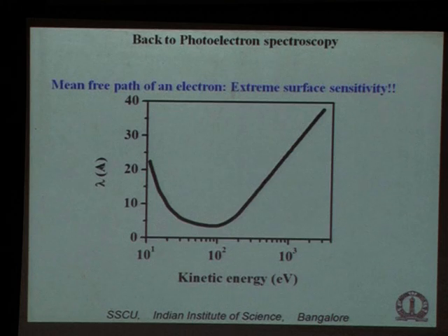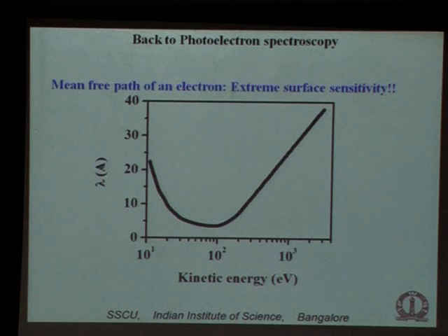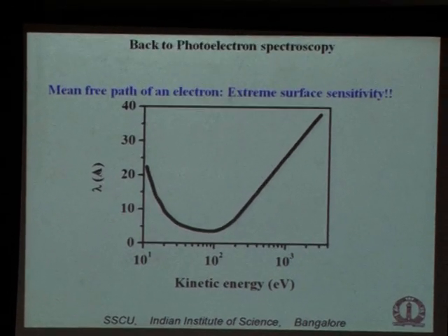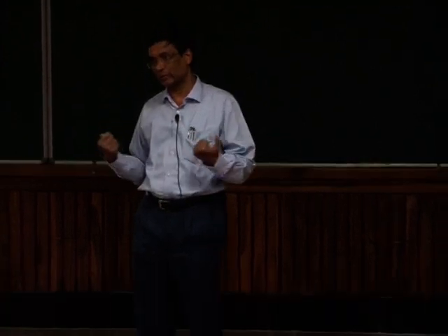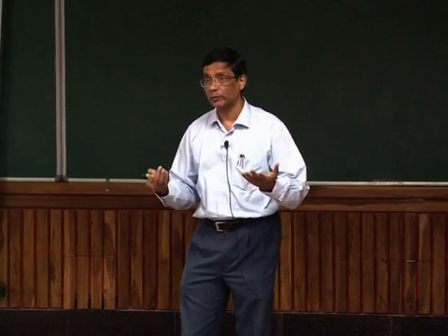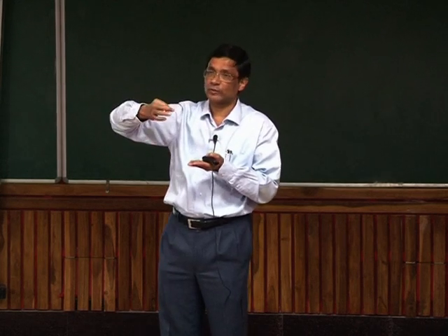Question, Didi. Yeah. So do you have space resolution? Can you talk about local density of states, at least at a coarse grain level? Yeah, we can, with, of course, the limits and limitations. The kind of local density of states that you can talk in terms of STS, scanning tunneling spectroscopy, is really the local density of states. What you can talk about, because the photon can be bunched together, the best that you have done, and you have done quite a bit of experiments on that, is down to about 0.1 micron, 100 nanometers. So you can do space-resolved spectroscopy with a resolution of about 100 nanometers.